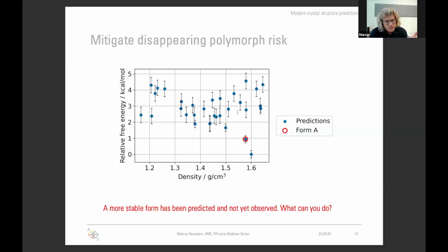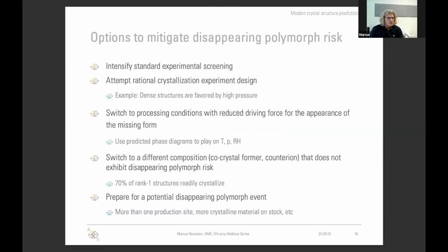I have to say all our error bars are 1 sigma error bars, so we are not at the error bars of the engineers yet, which are often 3, 4, 5 sigma error bars. Then pharmaceutical companies will act on this. And they have a variety of ways how they can act on this. So they can simply intensify their standard experimental screening, or because we now know the crystal structure of the form that should be observed but has not yet been observed, we can try a rational crystallization experiment design to make that very form. Or since, as you will see, we have a certain control over the phase diagrams, we can try to go to thermodynamic variables like temperature, pressure, or relative humidity. That makes it more likely to observe the form.